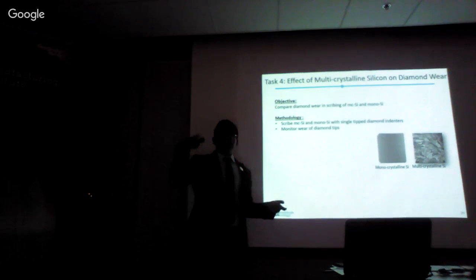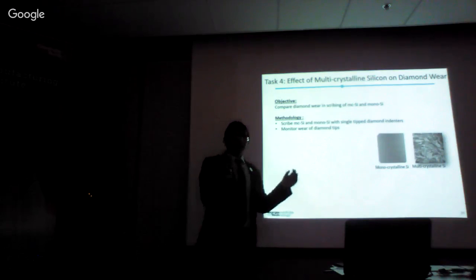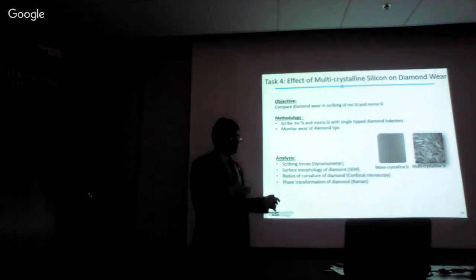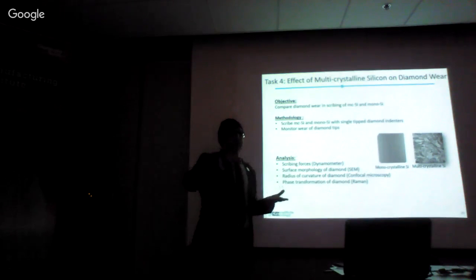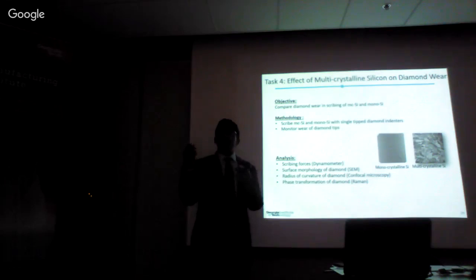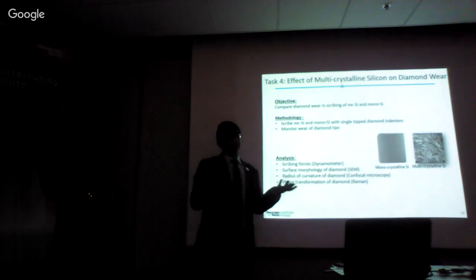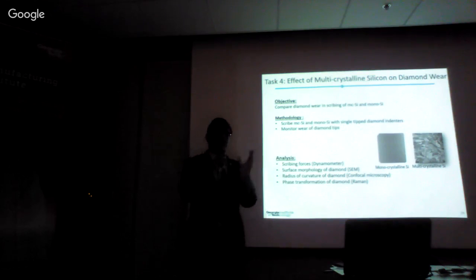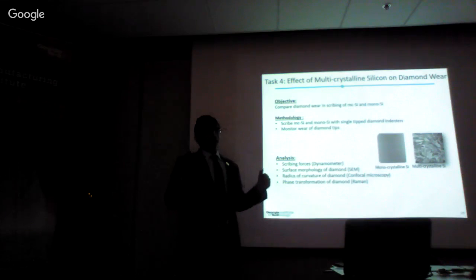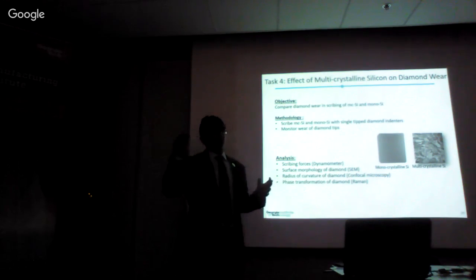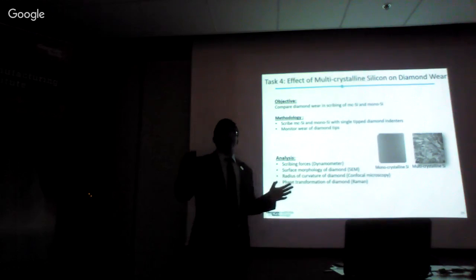We scribed multi-crystalline silicon and monocrystalline silicon with a single tip diamond indenter. One example of that indenter is there in the sample passed around. When we monitor the wear of the diamond due to multi-crystalline silicon and monocrystalline silicon, we analyze the scribing forces. If you remember in our setup, and I'll show it again, we had force being measured with a force dynamometer. We analyze the surface morphology of the diamond here, not the silicon, because we are interested in the wear of the abrasive diamond. Third, we find the radius of curvature of the tip of the diamond, and how it changes with more scribing for multi-crystalline and monocrystalline silicon, so that we can compare them quantitatively. And finally, we also do Raman spectroscopy on the diamond, not on silicon,